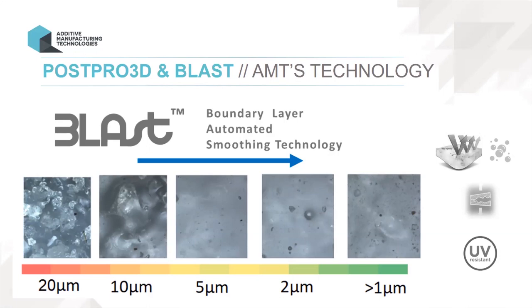And with that, you also see an uptick in UV resistance because there is a lot less moisture absorption at the surface, and there is a lot less exchange with the evaporation of that moisture and the sunlight affecting the mechanical properties of the material. So all the issues really start at the surface. Because of that, we have tackled the surface to provide this type of capability.